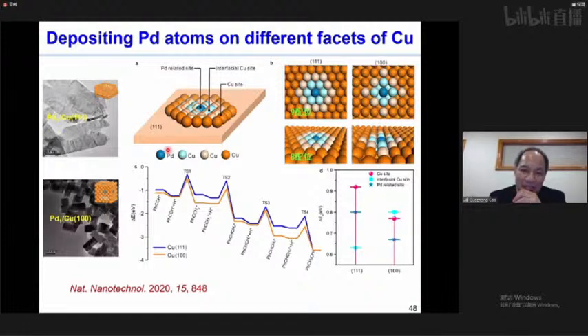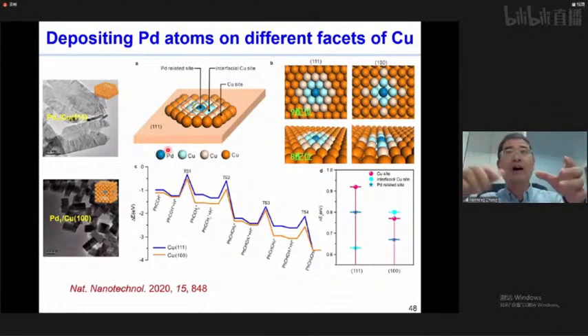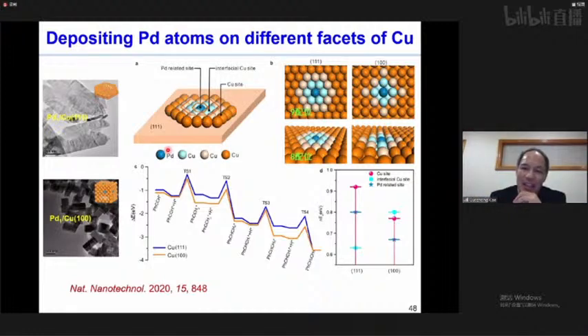Okay. Actually the 111 is hexagonal, but the 100 is a square configuration, right? In this case, our DFT calculation suggests that because of the difference in the coordination number, they change the bonding strength of the reactant on the surface. That's the main reason why we see the difference in their activities. Because the 111 surface is so condensed for the binding of phenylacetylene, it's not active for the hydrogenation, but for the 100 surface it is.